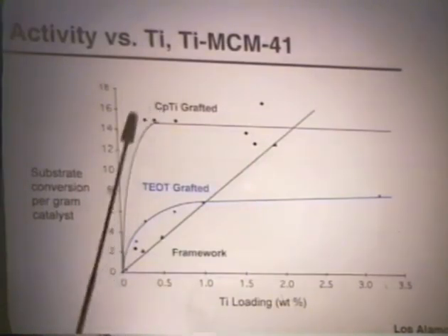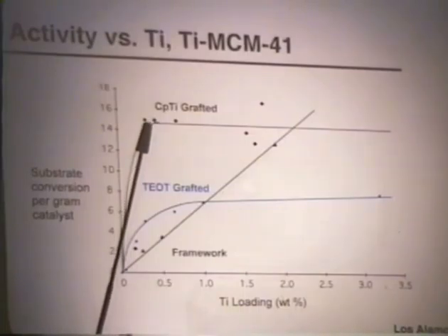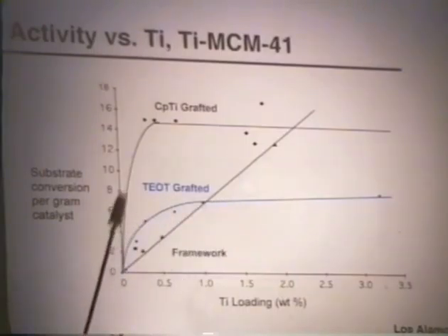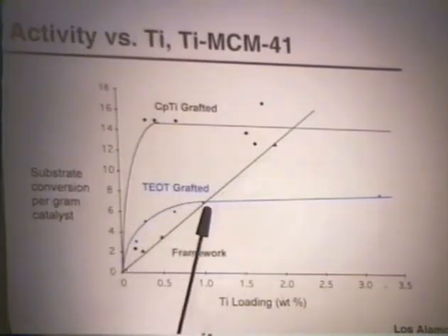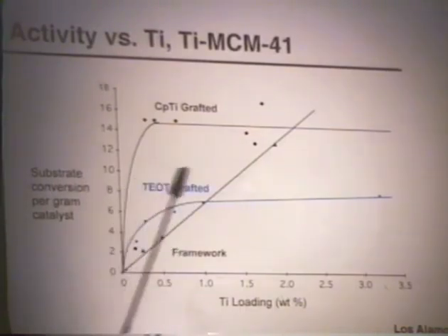The first type, which is where all the activity occurs, and then you're putting more and more titanium on, which is apparently not of appropriate geometry or whatever to give activity. The tetraethyl orthotitanate has the same sort of almost a titration curve appearance, however, at much lower activity. This is likely due to the coverage of active sites that are once formed, but then covered with oligomeric titanium from the tetraethyl orthotitanate that's still in solution.